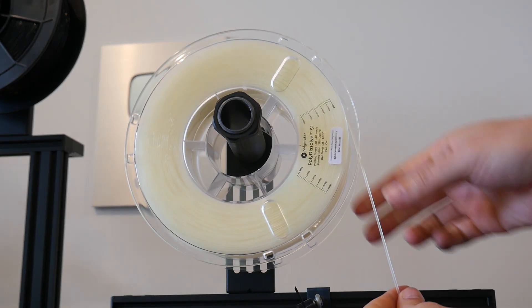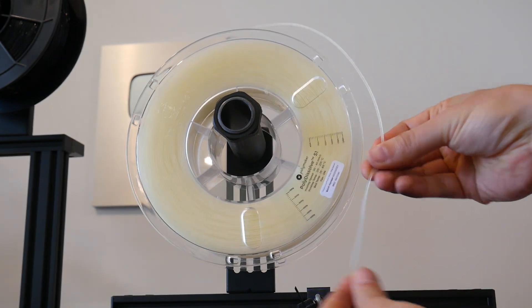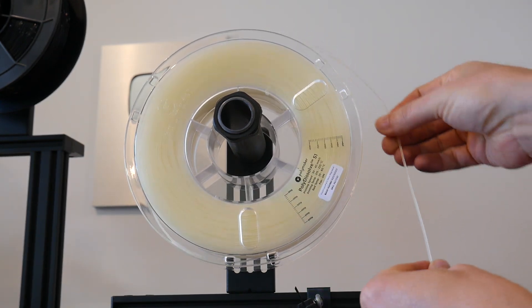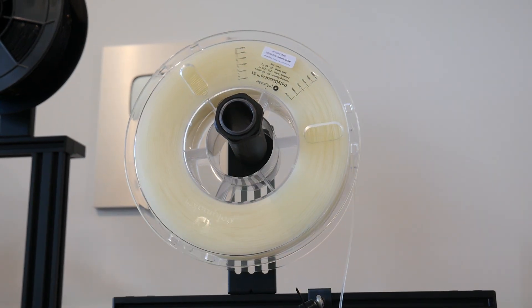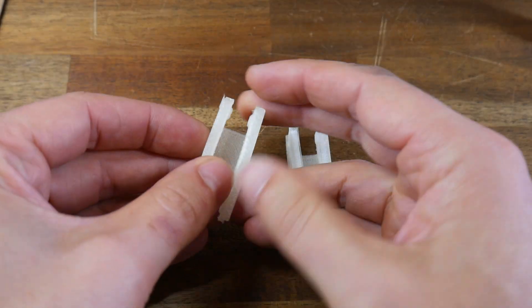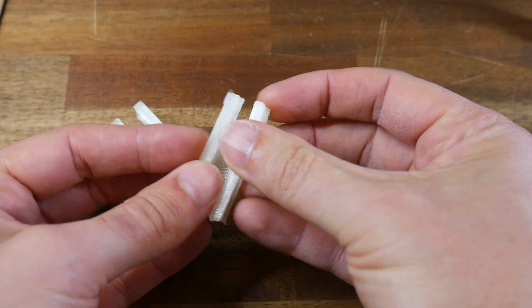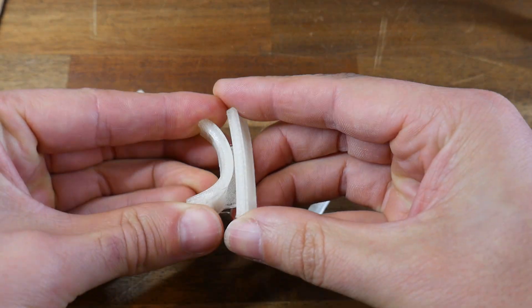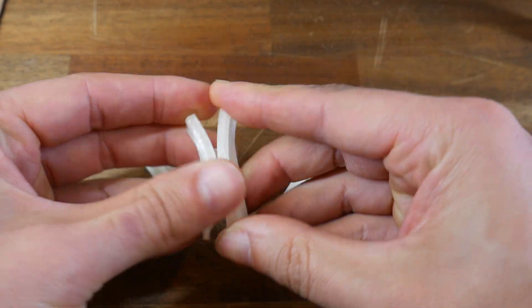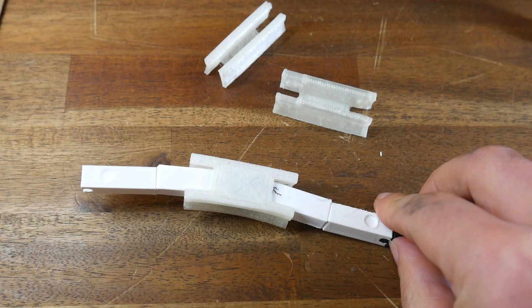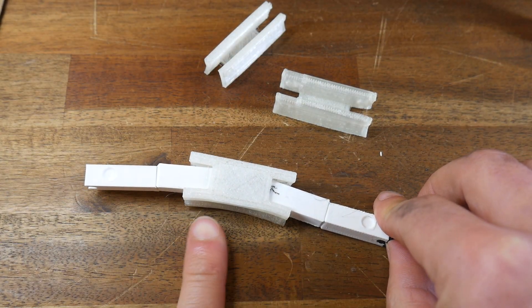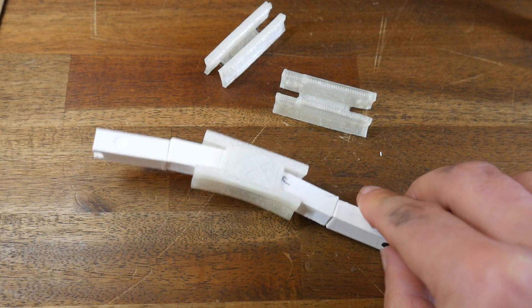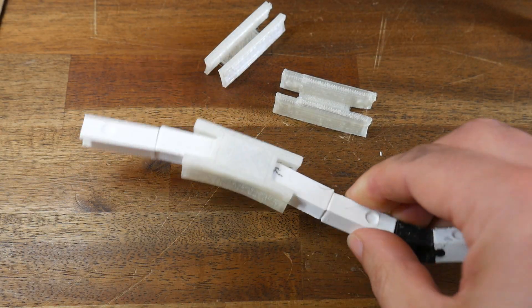You might have noticed these little bumps on the side of my PLA parts. They were designed to interface with this print-in-place locker. The idea being, after the joint had been straightened, these could then rotate down, locking the joint straight until they dissolved. What I discovered, however, is that dissolvable support material filament is as flexible as TPU. I went through several iterations trying to make this part thicker and thicker so it wouldn't bend, but this was futile.